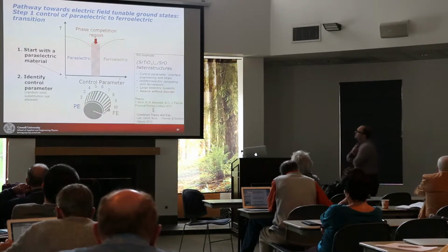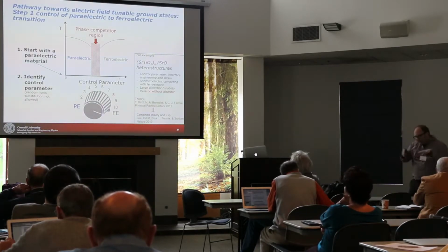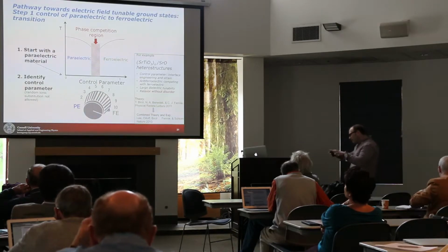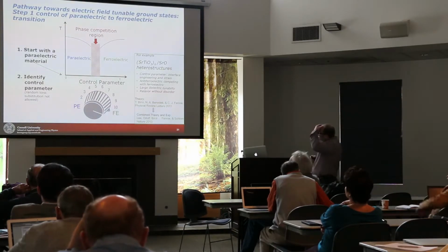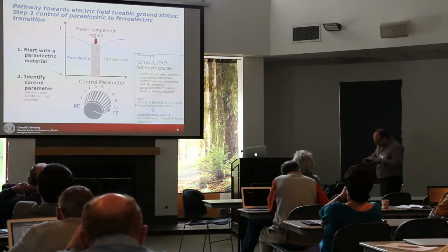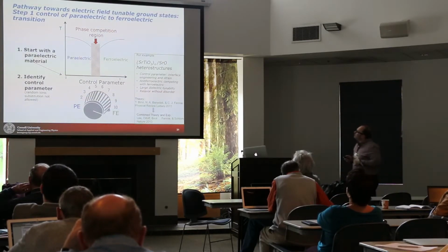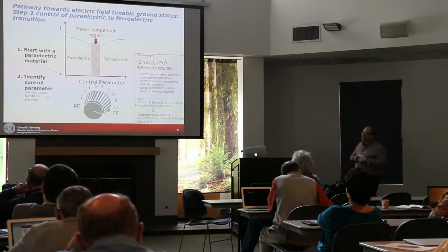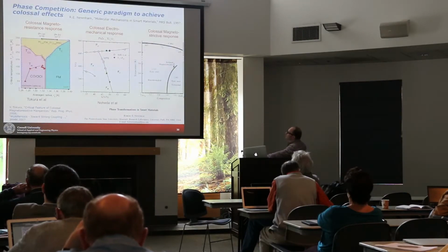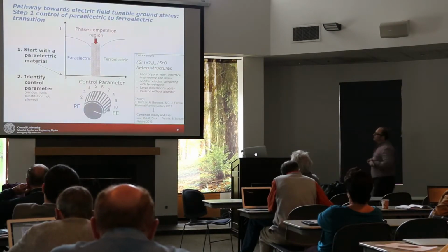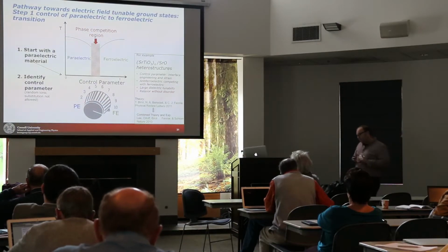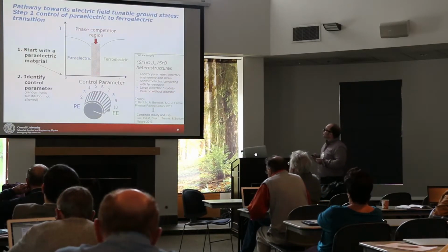Very schematically, what's going to be key to everything I'm thinking about, in order to take this electric field and have it couple to the underlying degrees of freedom, is the idea that underneath, the material we're creating is a ferroelectric. In fact, the starting point is a material that is a paraelectric, and we design a way of controlling this paraelectric to ferroelectric transition. We've seen examples before in PZT. That's exactly what's going on. We're using chemistry to do this. We don't want to introduce any disorder. We don't want to just make random alloys. We want to find new control parameters in order to tune to phase boundaries.